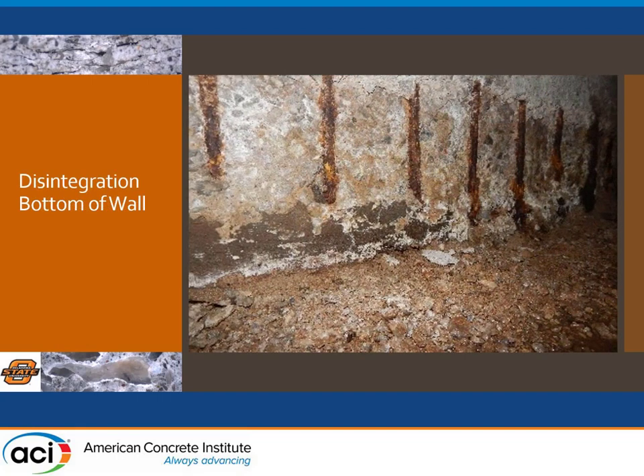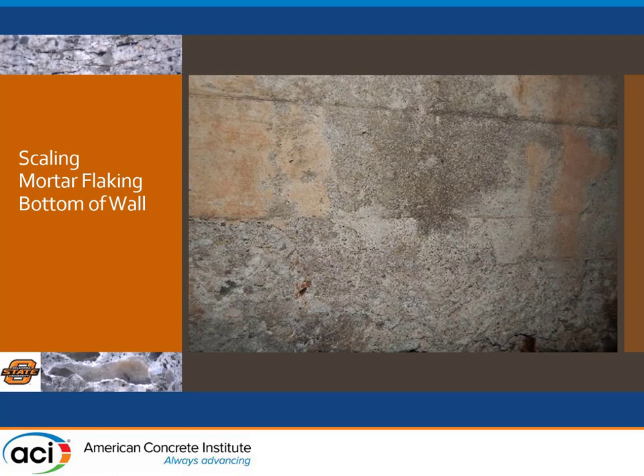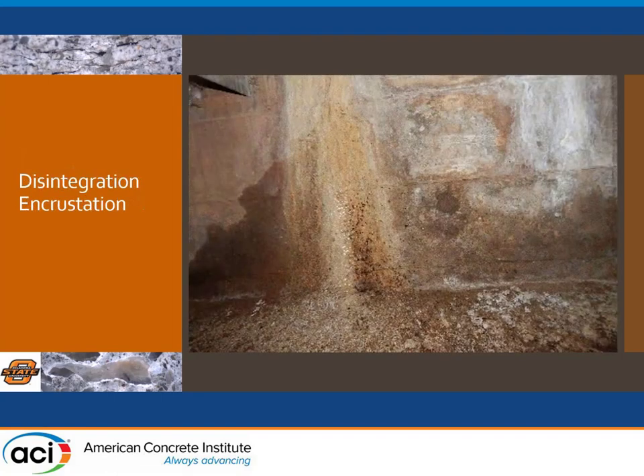Getting closer, we can really see salt crystallization and scaling due to salt crystallization, along with the common disintegration that comes with it. At the bottom sections further into the tunnel, there is severe disintegration with accumulated material that was never removed over time. Along defective joints and cracks, with all of the water coming in, we're starting to have encrustation — no longer just salt crystallization, but a hard coating of material basically stuck there that we had to remove with a hammer and chisel.